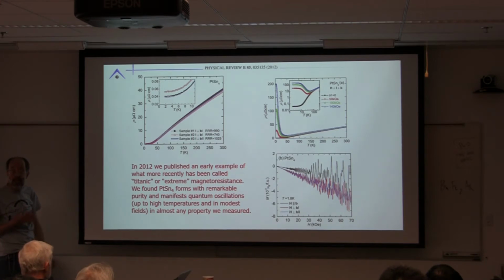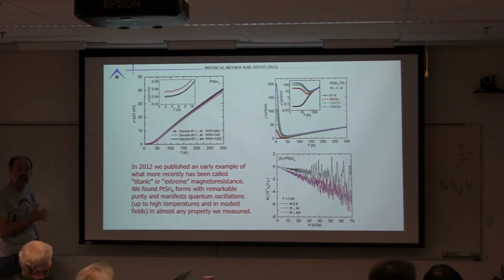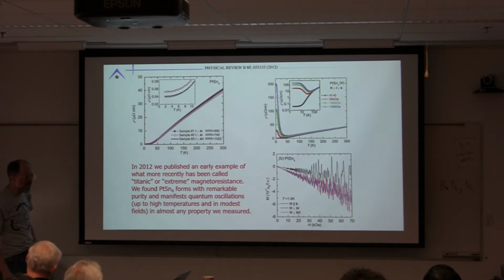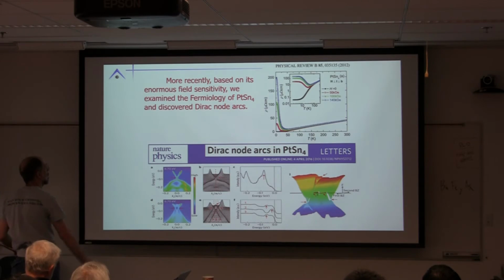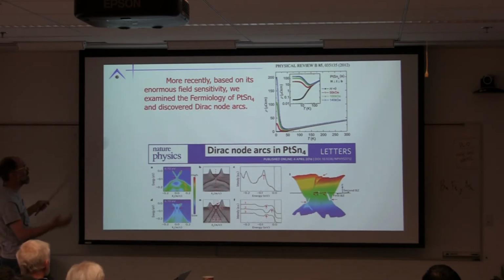We found it an interesting material, and one of many materials that we had looked at over the decades that were sort of semi-metallic and had anomalously large magnetoresistances, and we filed away as, why? That's weird. What's going on? And basically, with the advent and our ongoing understanding of Weyl-Dirac topological materials, I'm seeing a strong correlation between materials that have anomalously large magnetoresistances and interesting topology or fermiology.